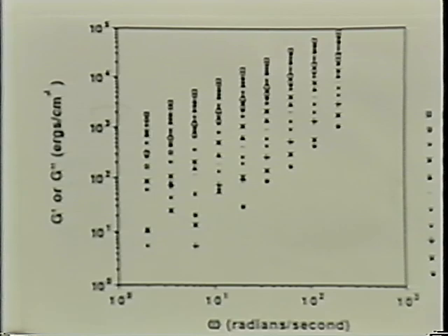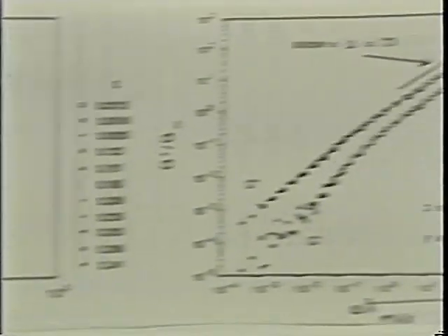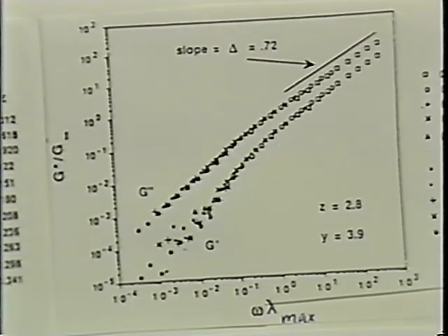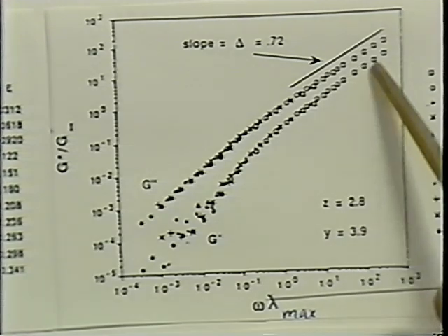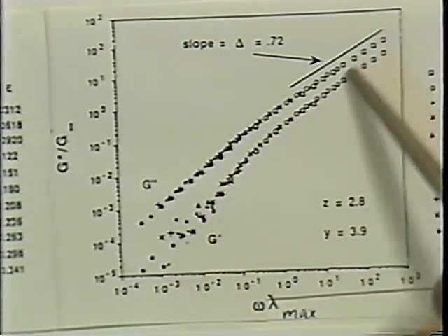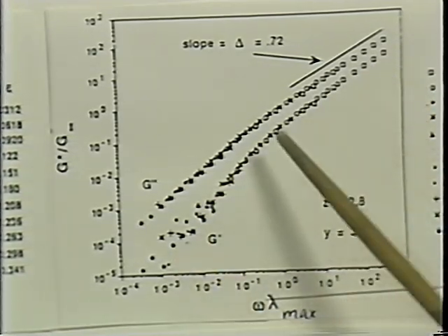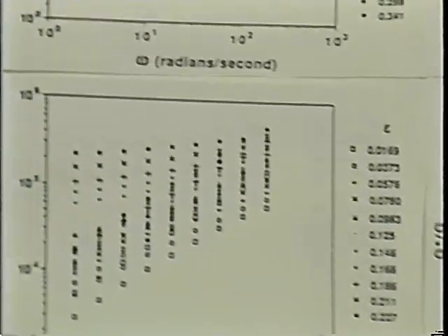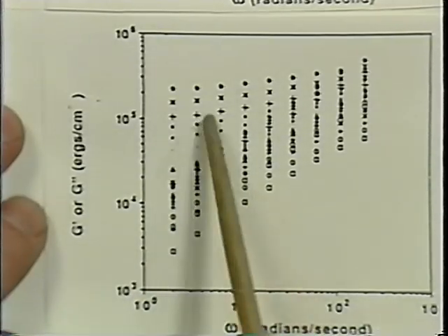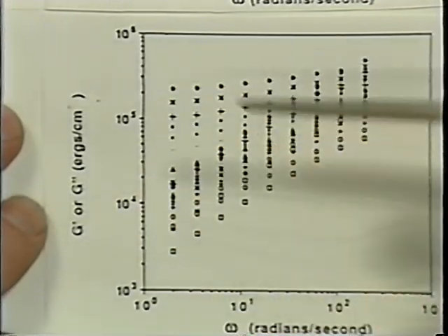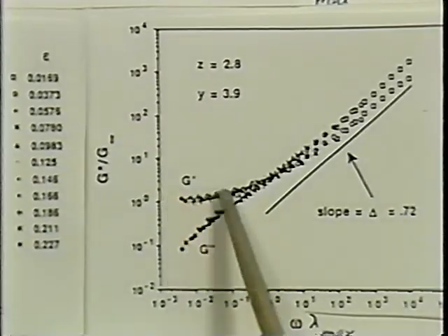And they were shifting those data now into a set of master curves over a very wide frequency window, which they could never measure in reality. And this would be the typical fingerprint of G prime and G double prime in the system, or vice versa. And they do the same thing here for the material in the gel. This would be typical gel behavior, and close to the gel point, everything comes down, and they're fitting all of this into a set of curves.